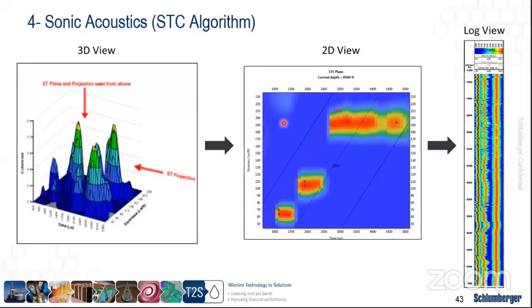So by just looking at this coherence map, we can identify the compressional slowness, which in this case, for example, is reading around 60 microseconds per foot. And then we can identify the shear slowness, which is reading around 105 microseconds per foot. And then later in time, we can identify the Stoneley slowness, which is around 200 or 190 microseconds per foot. And we just do this for each and every depth in order to come up with what we typically see when it comes to array acoustic waveform. This is just the basics of acoustics.